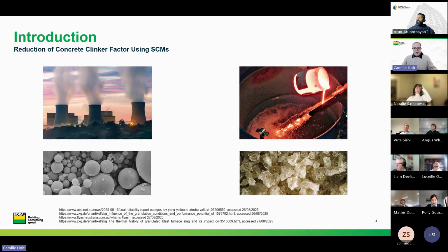And there are a plethora of materials which have been studied as partial cement replacements and have been reported in the research literature. Many of these are waste products or byproducts from other processes, which is fantastic for circularity. However, many of these materials can suffer from two key drawbacks. Either they don't allow us to replace a significant enough amount of our cement, or the supply isn't sufficient. Maybe the supply is localized in one geographical area, or the volumes of material available aren't sufficient, or the quality or volume might be variable, and we can't rely on having a stable source. So the question that a company like Boral must ask is which of the available materials are going to allow us to replace enough cement to appreciably reduce the clinker factor of our concrete, while also being available at the scale needed to meet demand for low carbon concrete into the future.